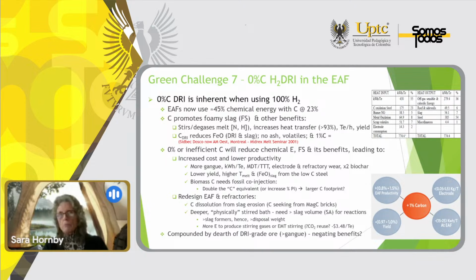There'll be higher temperature melting because with lower carbon, it will require higher temperatures. There'll be more FeO in the slag, excuse me, and the biomass will often need fossil co-injection, sometimes because of the nature of the biochar, but otherwise it's going to be a need because of the lack of biochar worldwide. We're going to have to redesign the electric arc furnaces and the refractories because there will be carbon dissolution from the current refractories that are used, and there'll be slag erosion.